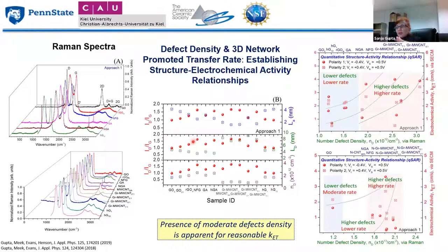From the fundamental perspective, because I always like to do some fundamental study along with the applications, we utilized all of these aerogels and wanted to establish what we call a structure activity relationship, or a structure electrochemical activity relationship. So we combined Raman spectroscopy and scanning electrochemical microscopy, because if you're studying carbon, you have to measure the Raman. The classic bands are the disorder activated D band around 1300, and the G band, which comes from graphite or graphene, that exists in any sp2 bonded carbon system. If you take any sp2 bonded carbon system, you must have a G band.